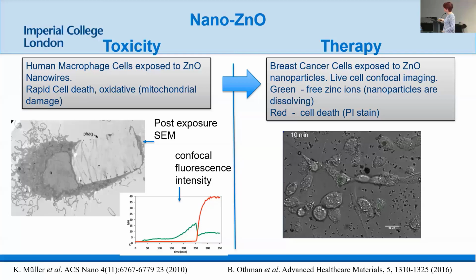And then taking this knowledge, we applied that to looking at some breast cancer cells. What you see here are some breast cancer cells on a plate. What we're going to do is expose them to zinc oxide nanoparticles whilst we're imaging them. And again, we've got these same two dyes. If you see it go green, that means the particle has dissolved, right, and released zinc ions. And if you see it go red, it means the cell is dead, right?